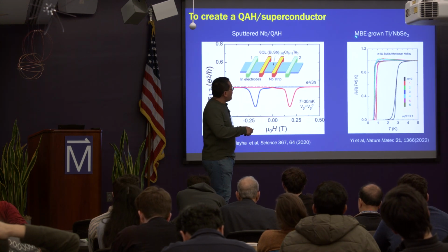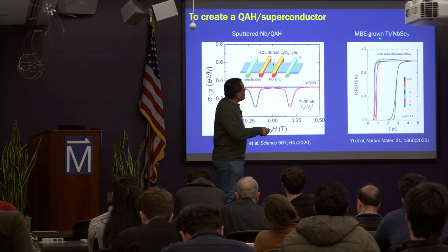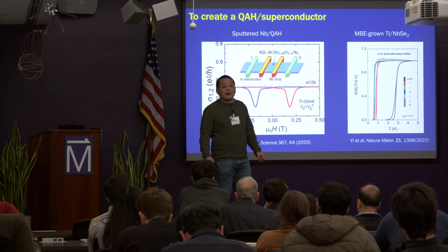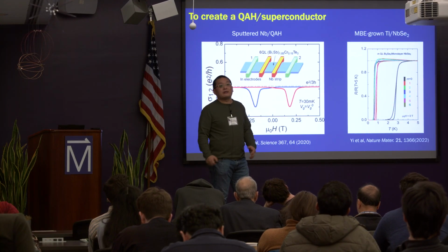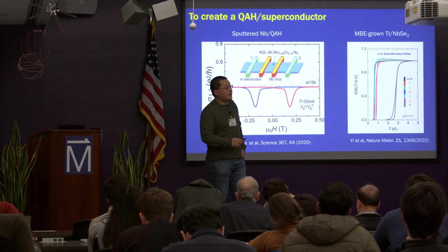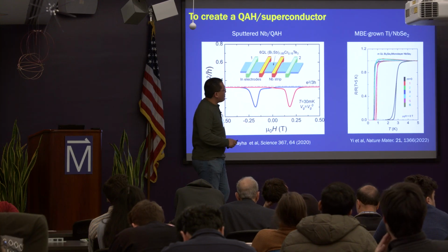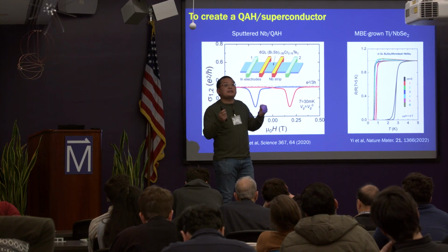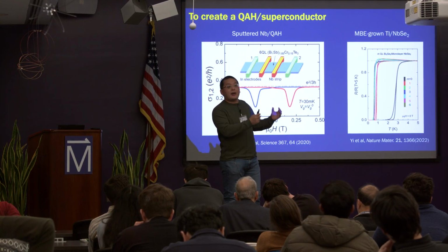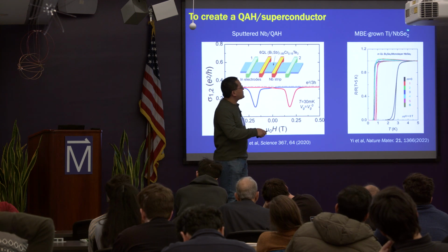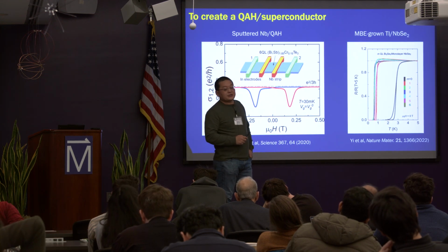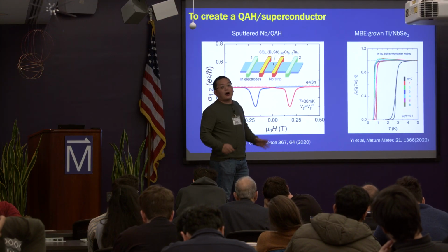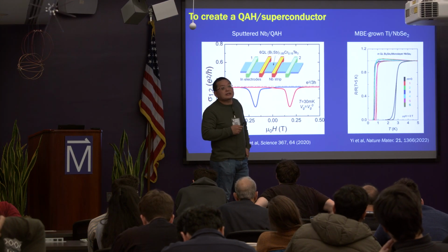If we could grow the magnetic TI and niobium heterostructure within one MBE chamber with a sharp interface, that's the best quality for the exploration of Majorana physics. But the topological insulator has a hexagonal lattice structure. From traditional MBE knowledge, we need a superconductor also with a hexagonal lattice. If we exclude the single-element superconductors, there are only two or three superconductors with a hexagonal lattice.